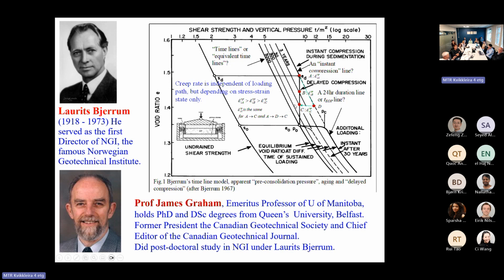I can get the strain rate here. You can see I have an epsilon VP dot C here. From here, I can get a viscoplastic strain rate. I can do another test: you can do the loading test from here, then do the unloading to the same point. So you can reach this point through the quick test from here to here, or you can also reach the C point from loading, unloading, to the same point. Two different loading paths actually reach the same point.